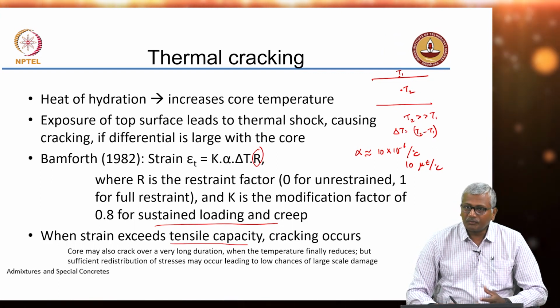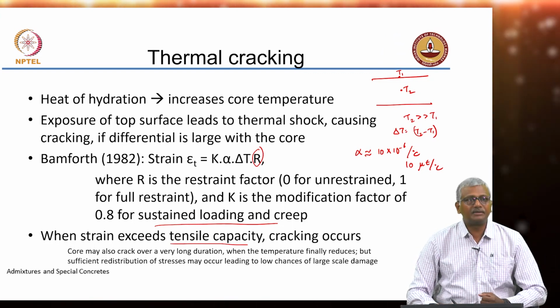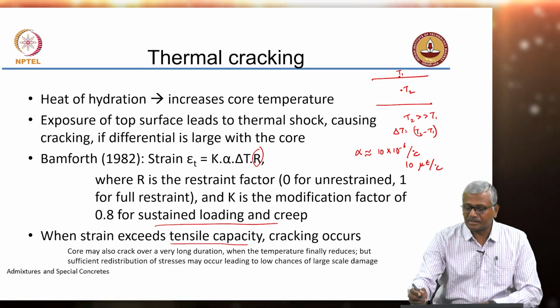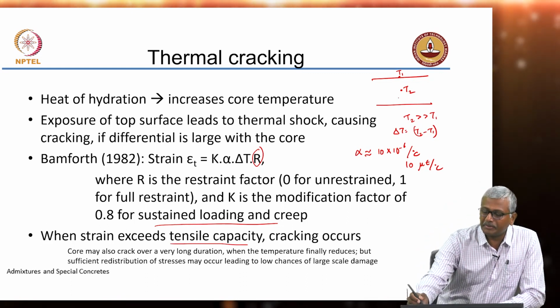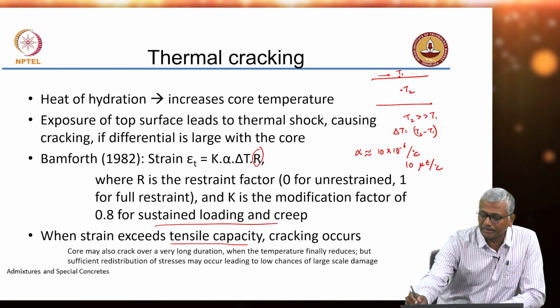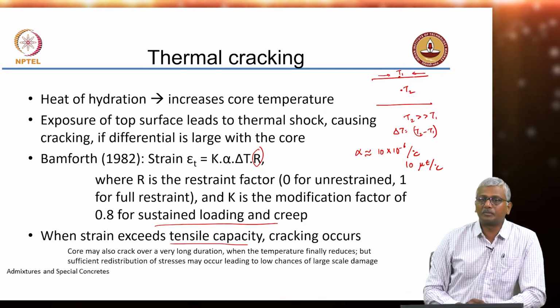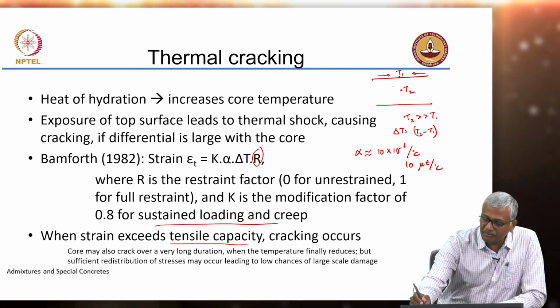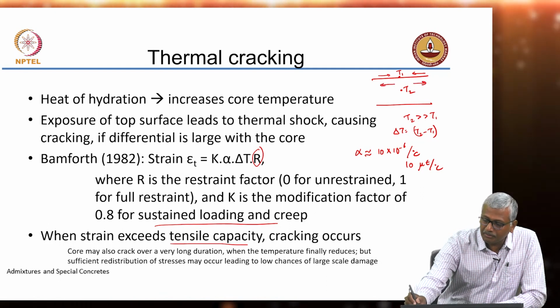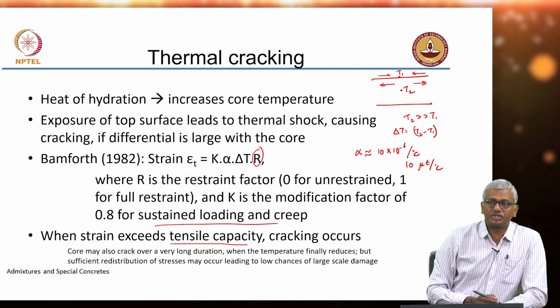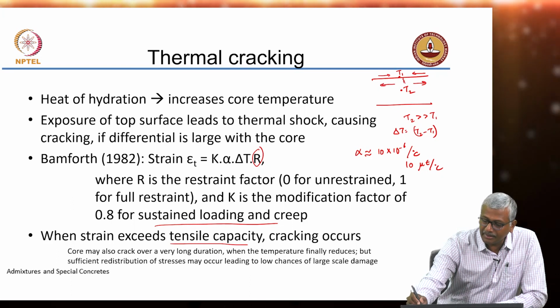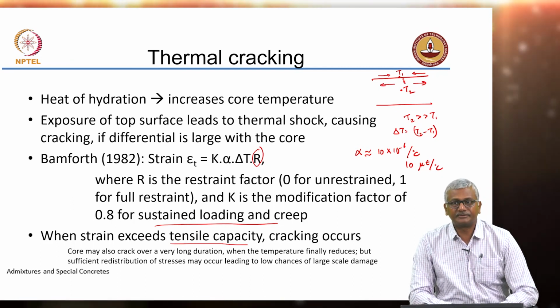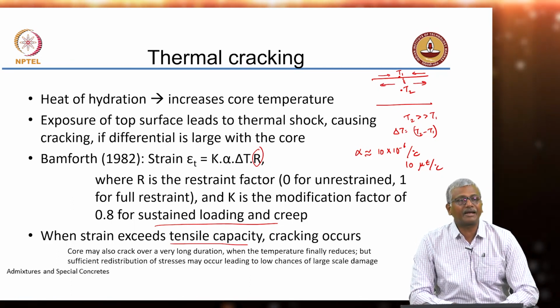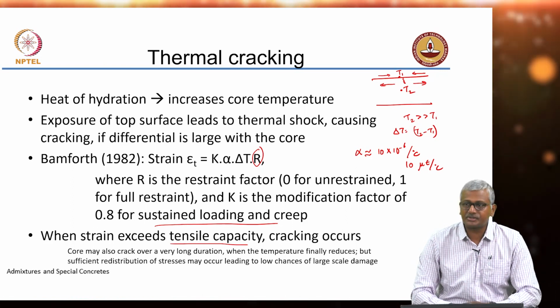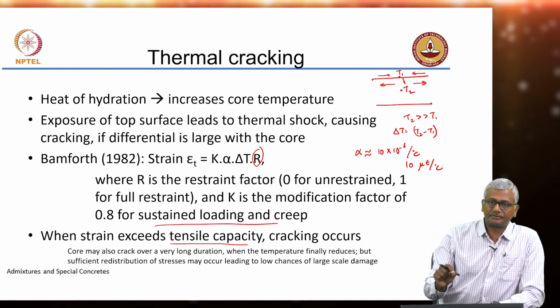Now, what we are not thinking about is that this is only at the surface. So, where will the cracking appear? It will appear at the surface, because the surface wants to contract, because low temperature is there. Core is preventing it from contracting, causing it to become a zone in tension. So, that is why you get a cracking on the surface. Okay. So, thermal cracking because of temperature differentials occurs at the surface.